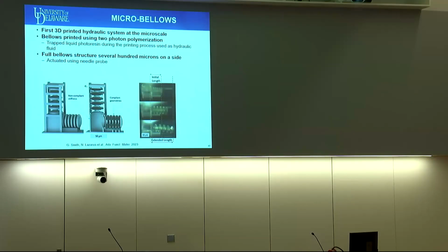Using this, we leverage the inherent properties of 2-photon to capture fluid at the microscale. The way 2-photon works is that you're using the laser to solidify material within a droplet of photoresist. Traditionally, you then remove that resist. But if you deliberately create a bubble or a structure that captures that resin, you can use that resin from the printing process itself as a hydraulic fluid. And so we're able to create a full bellows structure, several hundred microns on a side, that we're then actuating using a DC needle probe. We're pressing on the top bellows and moving fluid into the second bellows.